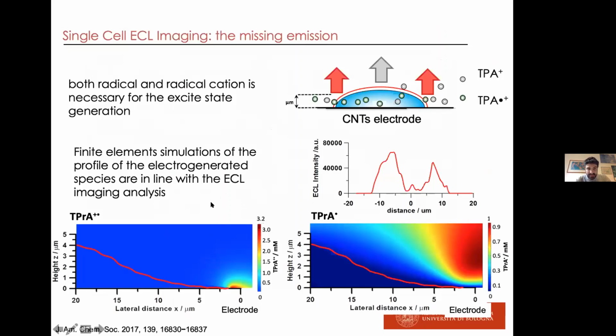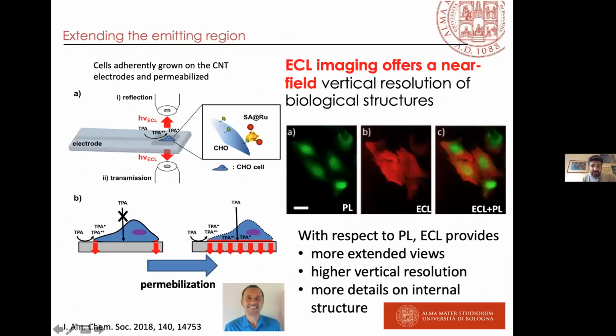We always try to combine, in different fields of application, ECL and ECL microscopy with finite element simulation. So these are COMSOL simulations, and you see here the radical cation concentration profile and the radical concentration profile. In this case, the red border is the cell border, so you can visualize up to where you can reach the ECL emission for the cells. Our experiments were in line with the simulation, and in this first study, we can visualize the first 5 micrometers of the ECL layer.